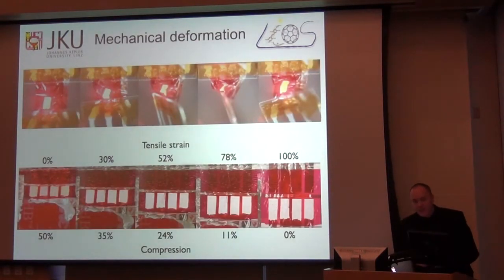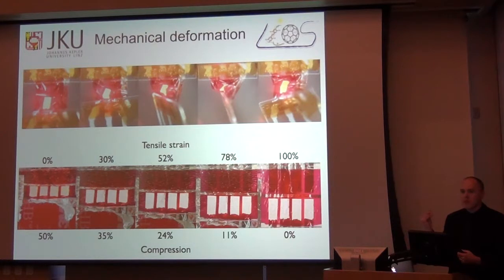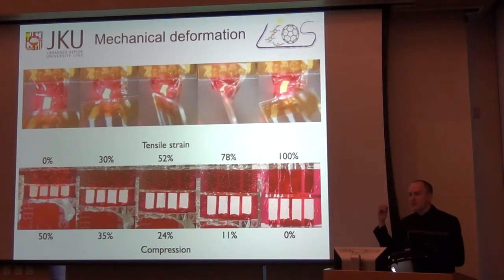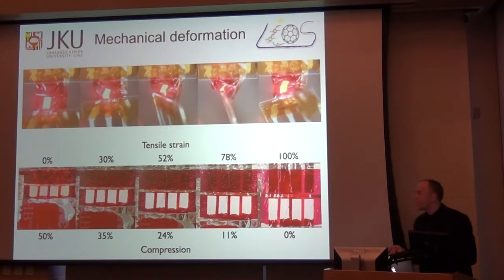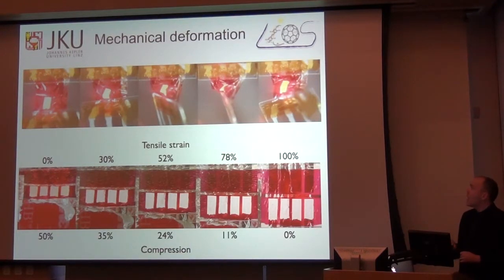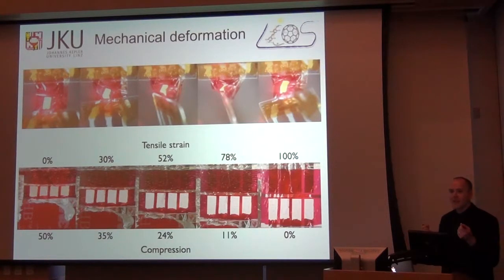For the mechanical deformation of these LEDs, we can literally crumple these LEDs in freestanding foil configuration as much as you want. I have it suspended in the top row between two pieces of glass, which I then bend and twist and crumple. But you can peel off the bottom piece of glass and crumple the LEDs between your fingers just like a tissue, and they work just fine. There's no deformation whatsoever, no damage. If you rip the device, it will rip in an instant because it's a very thin film. But from crumpling, no problem.